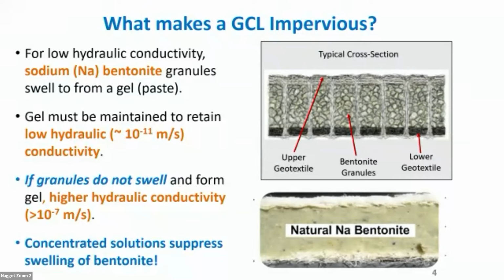The product looks like this when it's delivered to the site. We've got that granular bentonite sandwiched between two geotextiles. We're rolling it out in the ground. It has to hydrate and transform itself into a gel like we see down here. And whether that happens or not depends entirely on the geochemistry.